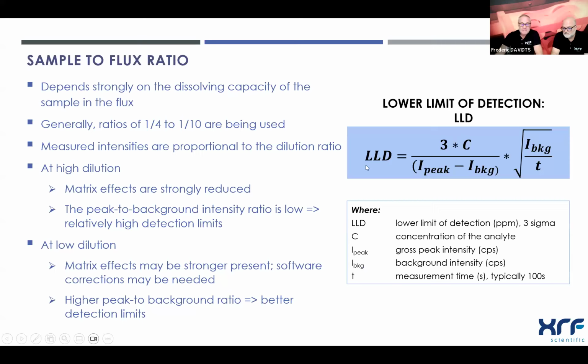The lower limit of detection is really defined by the peak to background ratio, but also by the measurement time. So we can see when we have a high peak and a low background, we have a very good lower limit of detection. Now this lower limit of detection can also be steered by the measurement time. If I measure a factor 4 longer, my lower limit of detection, being a square root function, will be 2 times better. So the lower limit of detection depends on the sensitivity of the elements in the sample and the measurement time.